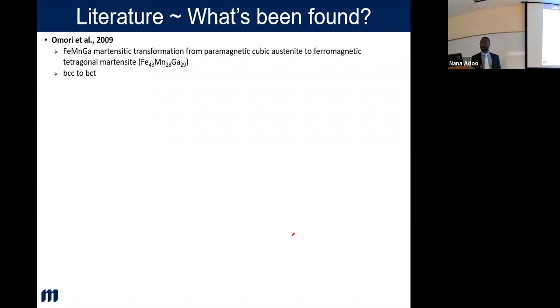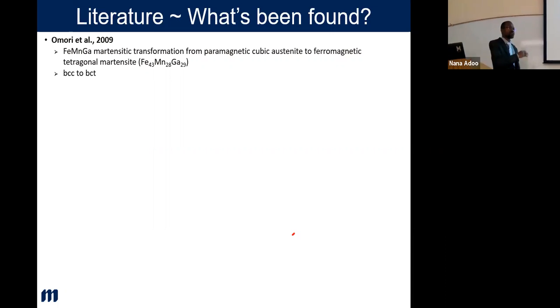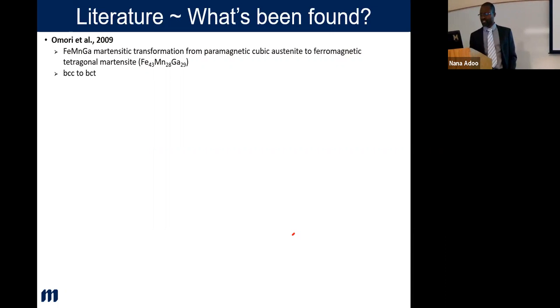And he found this within this composition range. This composition and the compositions are actually guided by a valence-to-atom electron ratio, or in other words, you have to have an electron density before you could actually get these things in a position where, or in a map where they're going to work.